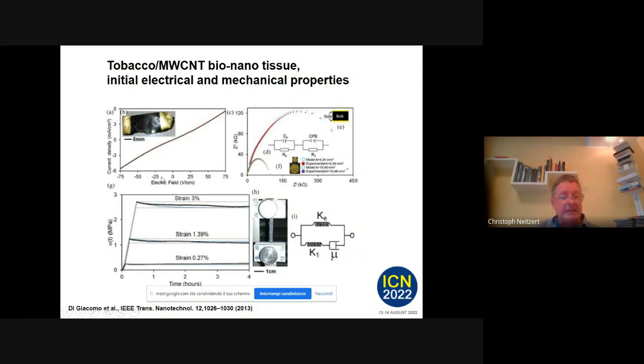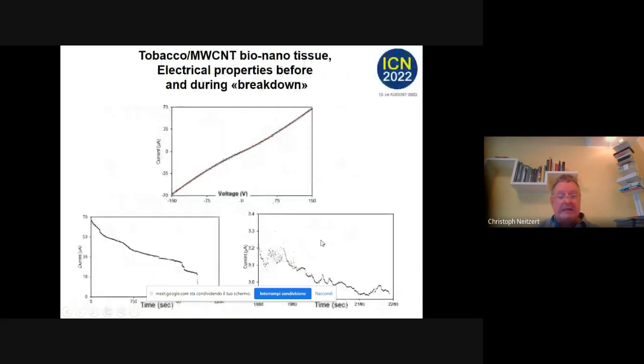So you see, no, it's not volt, that is the current density and electric field. So it's conducting, but it's not good as a heater. The conductance is not high enough for that. We measured the AC characteristics, where we can calculate the elements of the AC circuit, and we measured strain, mechanical characteristics, and this has very good mechanical characteristics.